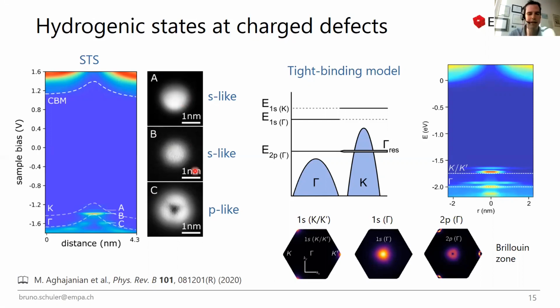So they have S-like and P-like wave functions. And then together with the group of Johannes Lischner at Imperial College London, we can model this with a very simple tight binding model by in fact just assuming a point charge. And already this very simple model gives us a very good correspondence of what we see. So they could model even the STS along the line here and all the states.